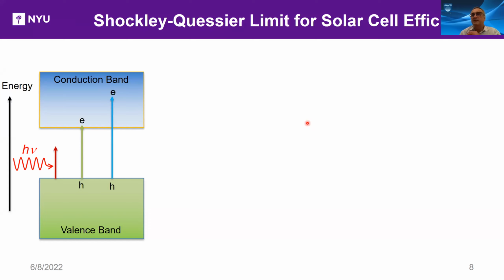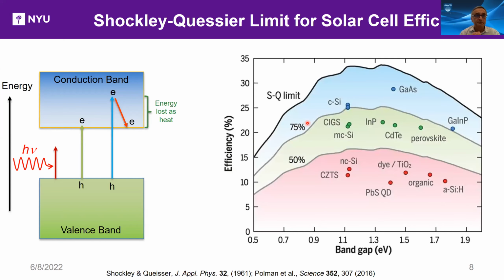If the light that comes in has energy greater than the band gap, then one creates hot electrons and hot holes. And when they relax very rapidly by colliding with the lattice atoms to the band edges, the extra energy that they had over and above the band gap energy gets lost as heat. Basically, more lattice vibrations are created, and that appears as temperature or heat in the solar cell.